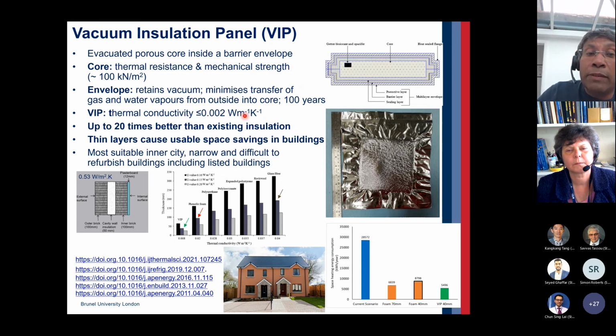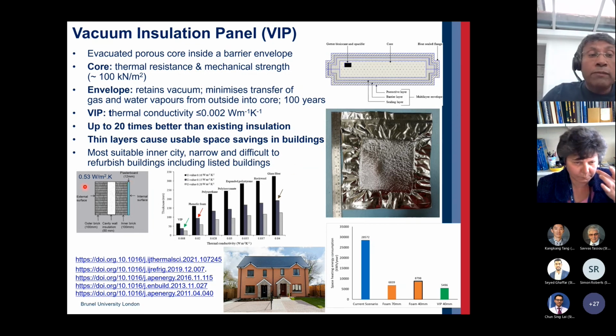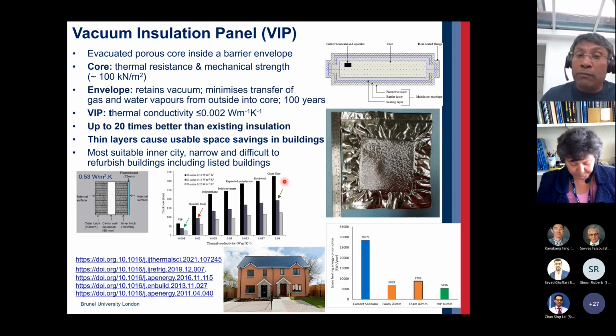Because of this low thermal conductivity, the benefit is that you can use very thin layers of it to produce a similar U value to that produced by larger insulation thickness layers. The example is shown here. For example, if you want to convert a 0.53 watt per meter square Kelvin U value, a typical UK dwelling wall, to a low U value, let's say 0.15, then a VIP of about 35 millimeter thickness will be sufficient, compared to about 100 millimeters of phenolic foam and about 175 millimeters of glass fiber required. So there is a benefit, and that's why the buildings which are difficult to insulate, which have been left uninsulated, a lot of them are narrow buildings, very narrow buildings.